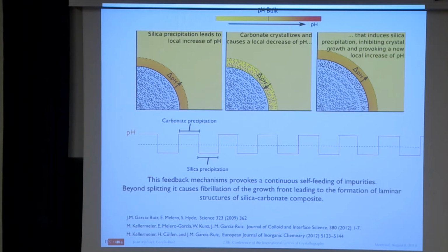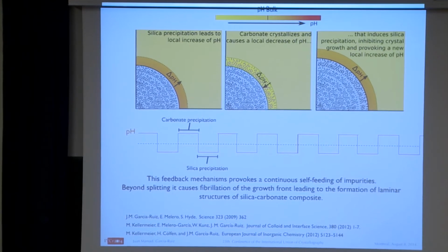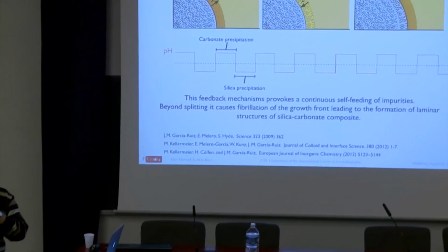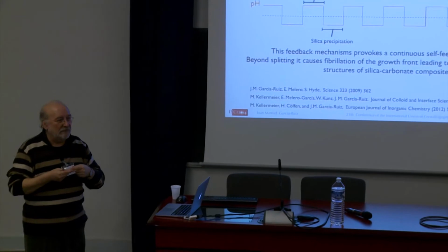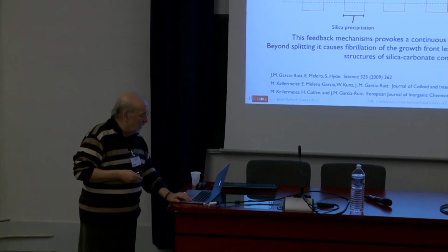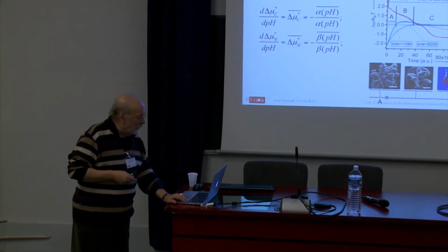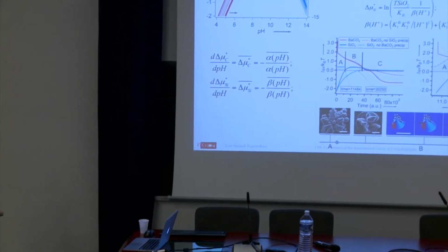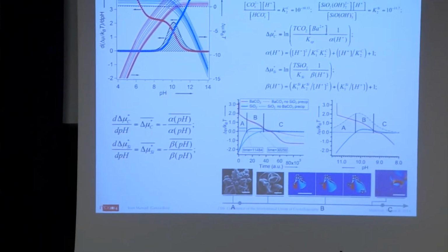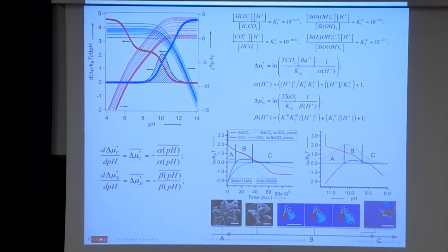is just to include a polymeric impurity with a crystalline phase, so that you could provoke the fractal branching, right? But the point is that in this case, the impurity is provoking the formation of the crystalline phase, and the crystalline phase is provoking the formation of the impurity. So you have a self-feeding mechanism, and this self-feeding mechanism, in our opinion, accounts for the formation of this biomorphic structure.